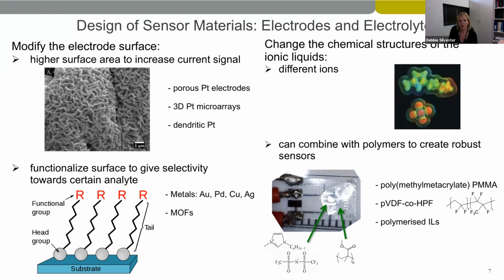So we're working with ionic liquids here. The most simple thing we can do is to change the ions of the ionic liquid. And then another thing that we can do is to combine with polymers to create more robust sensors. And so I'll talk about both of these today in the talk. But you can see at the bottom, the thin film electrode has a gel polymer electrolyte coated onto the 3 electrodes. And this is a mixture of an imidazolium NTf2 ionic liquid with polymethyl methacrylate. So I'll talk about these today.